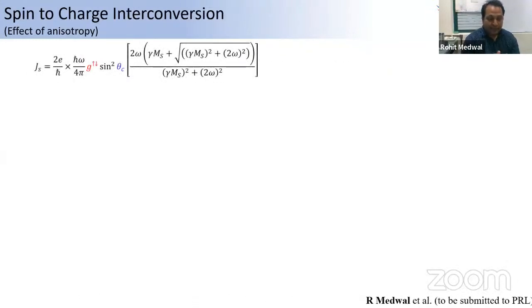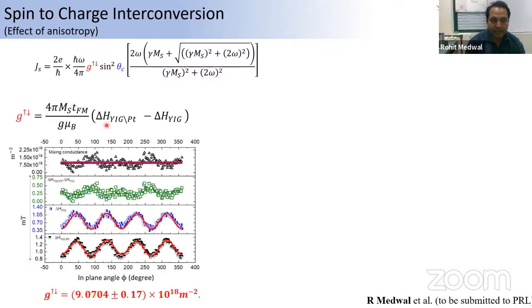So we try to deconvolute this. We can say that this is because of the anisotropy, but what is affected? Is the spin mixing conductance affected, or is the precession cone angle affected? We try to deconvolute the main cause of this modulation in the anisotropy field, or you can say the spin current. So we calculated the spin mixing conductance theoretically and experimentally, and within the error bar it is almost constant. There is not much change in the spin mixing conductance. I will not go into the detail of how we estimate it, because that is a very long process, but I would like to highlight that it is almost constant.